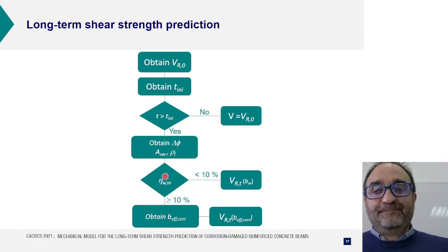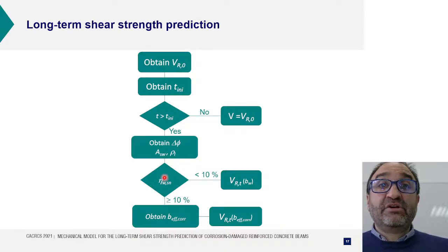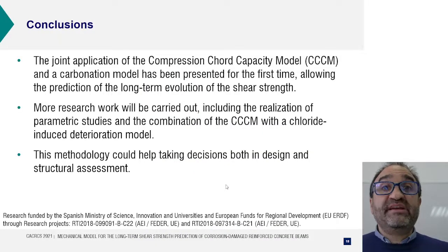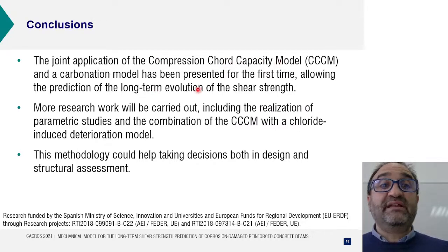If the reduction of the cross section of the stirrups is lower than 10%, then you can calculate with the original web width or the web width of the concrete flange. But if it's higher, then you will have a reduction in the width, and you can also obtain the strength here. So just to finish and to conclude, the joint application of the Compression Chord Capacity Model and the carbonation model has been presented here in this conference for the first time, allowing the prediction of the long-term evolution of the shear strength.